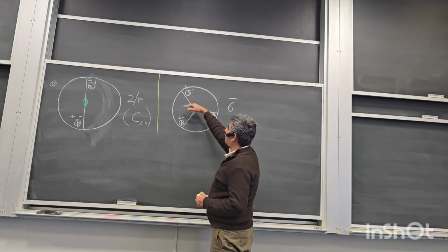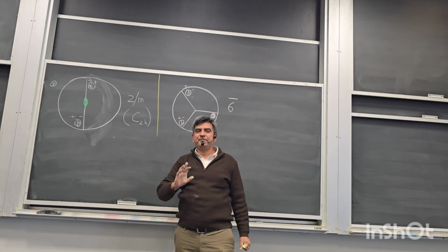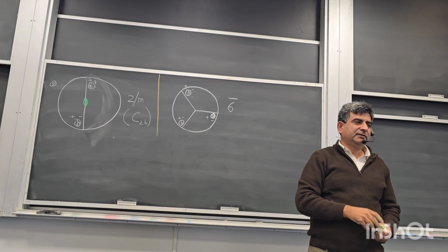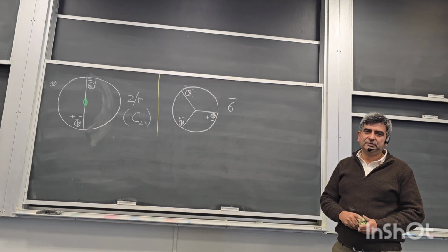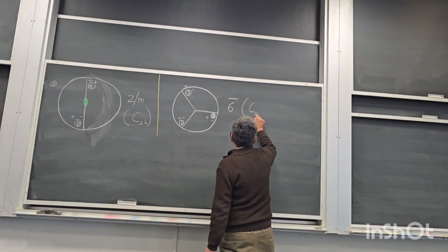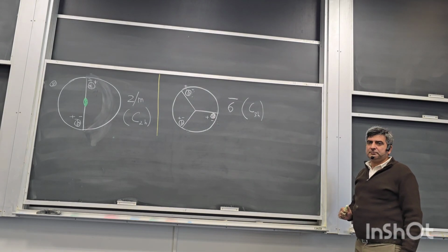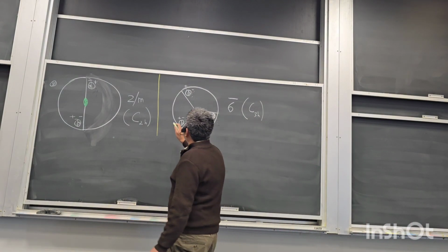And you can test this for all of these points. So this 6 bar is the same as doing a 3-fold rotation and a mirror plane that is horizontal. The symbol that is given to this point group is 6 bar. The old symbol, nevertheless, is C3H, the Schoenflies notation. Okay, so this was my 9th group.